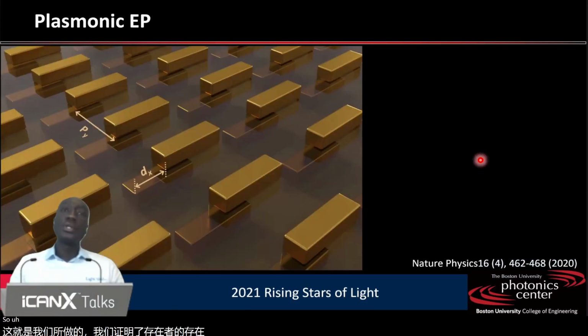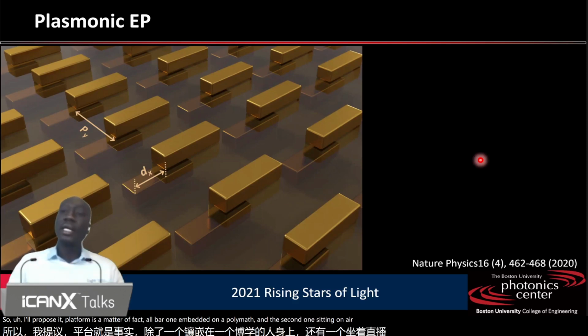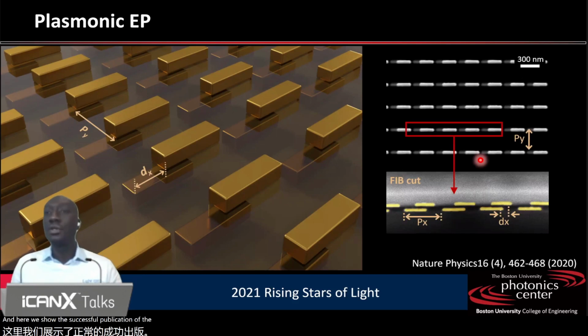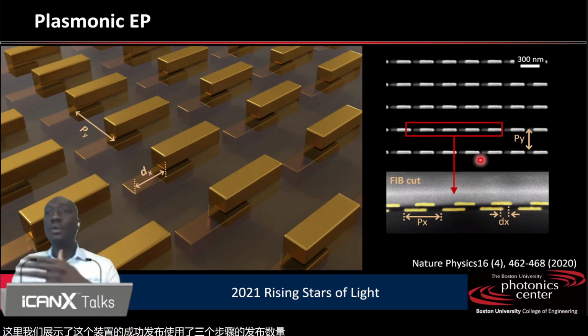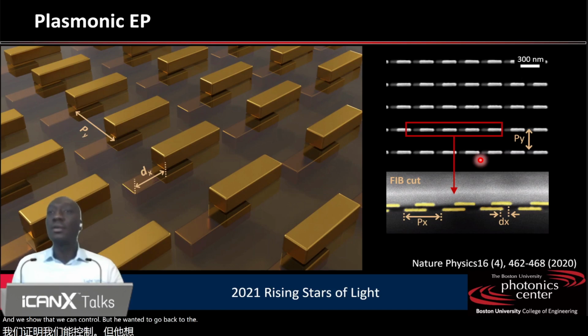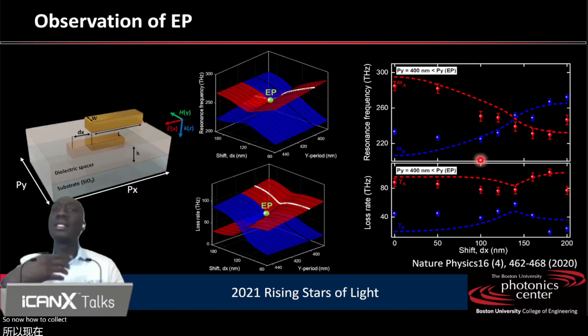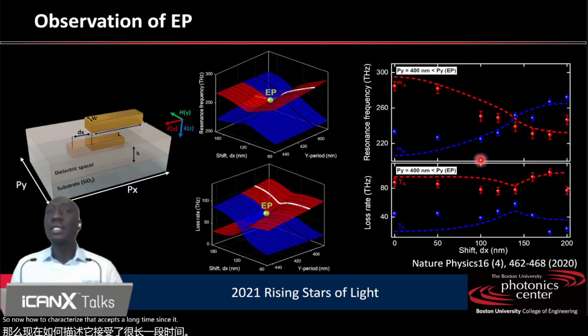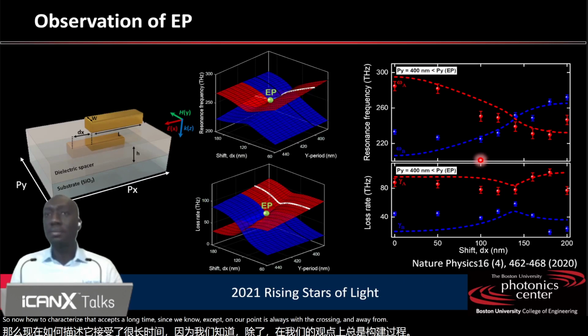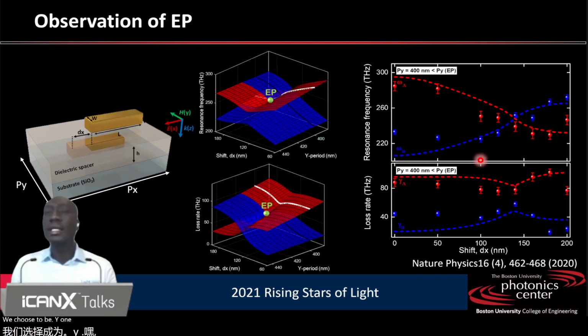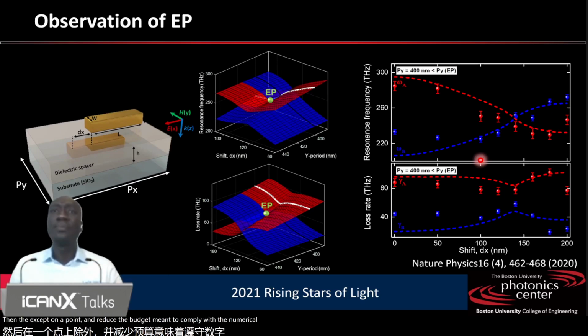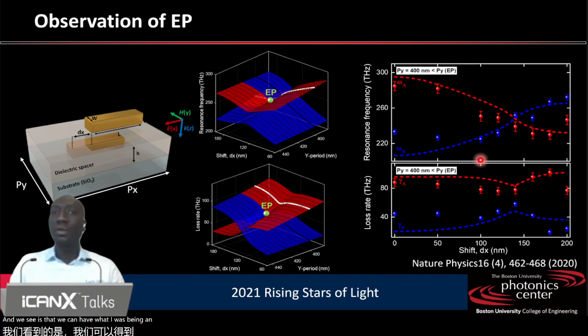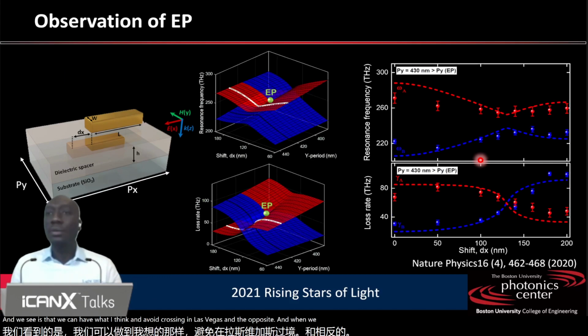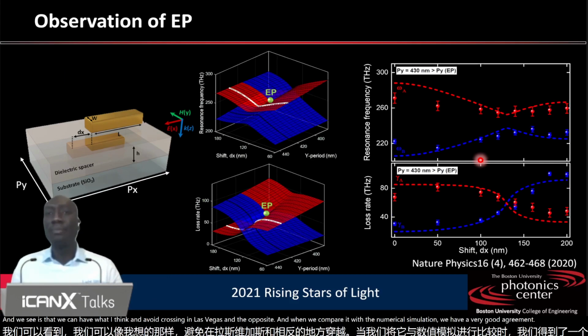So our proposed platform is an array of metal bars, one embedded in a polymer and the second one sitting on air. And here we show the successful fabrication of the nano device using three steps of nanofabrication. And we show that we can control very well the geometrical parameters of our structure. So now, how to characterize such an exceptional point? Since we know the exceptional point is always between crossing and avoided crossing, we choose two periods, one higher than the exceptional point and one lower, and we do the measurement to compare with the numerical simulation. And we see that we can have crossing and avoided crossing in loss rate and the opposite. And when we compare it with the numerical simulation, we have a very good agreement between them.